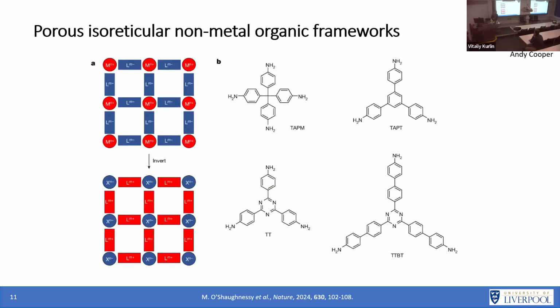So I just wanted to highlight a few studies for people actually within the department. It's worth mentioning these are not MOFs, hence the name, non-metal organic frameworks, but it is just to show the concept of isoreticular chemistry and how it can actually extend to related framework materials. So these are a series of essentially porous salts that were discovered by Andy Cooper's group and published just last year. And they're a similar concept to metal organic frameworks. In metal organic frameworks, we have these inorganic nodes connected by organic bridging linkers. In this case, you've got organic cations coordinated to halide anions to form these porous salt type structures. And essentially, you can do isoreticular chemistry with these as well. So you can keep the same architecture of the overall framework, but just change the linker in such a way. So it's just to show that isoreticular chemistry can be shown across a lot of different kinds of framework materials.